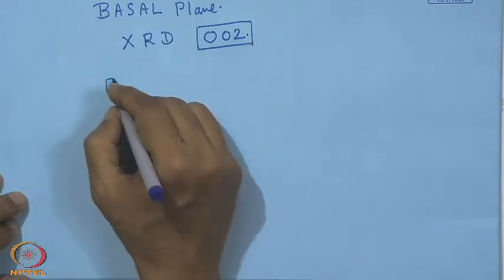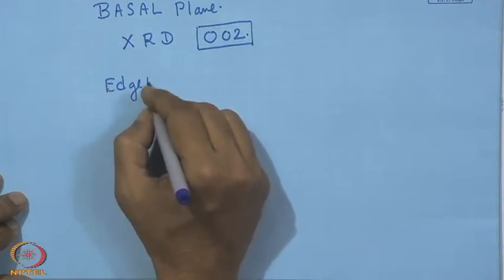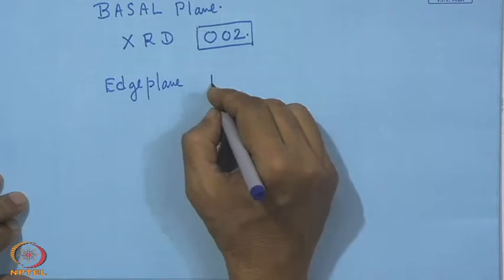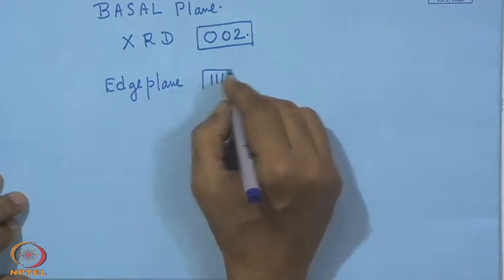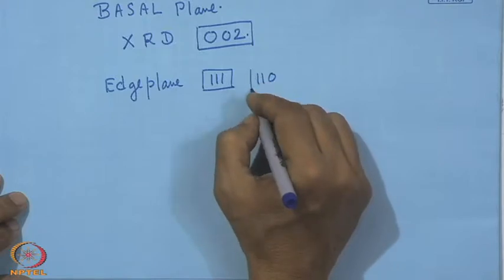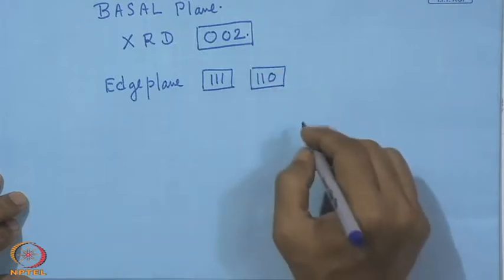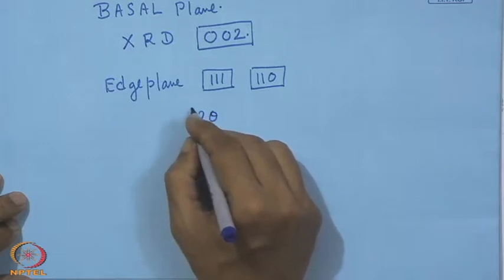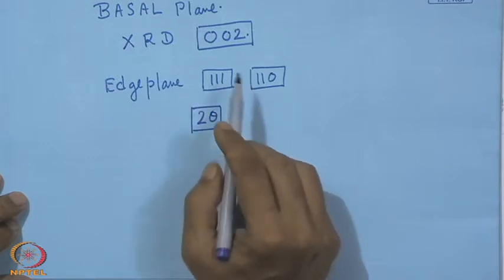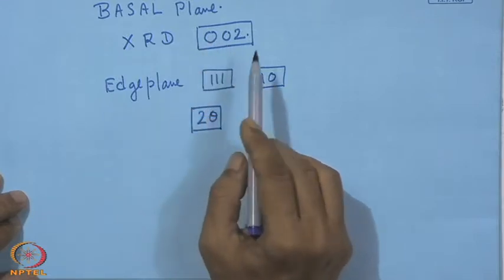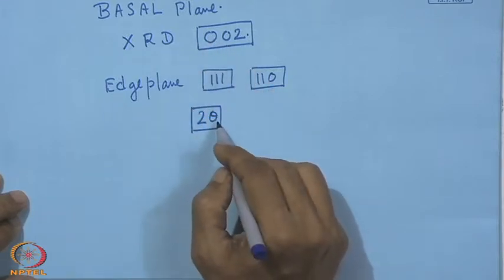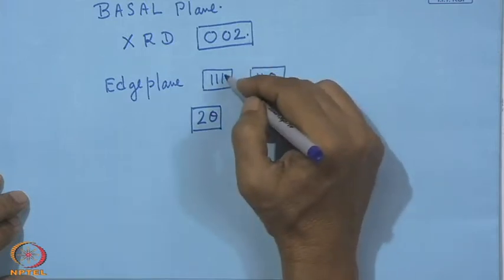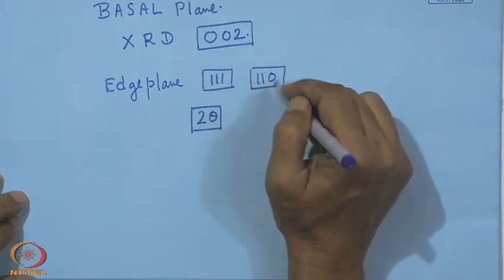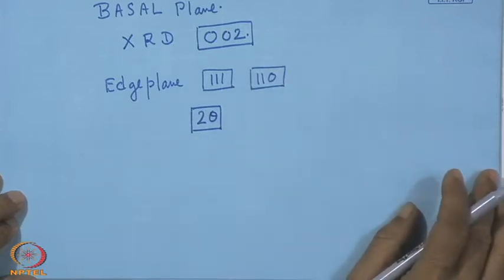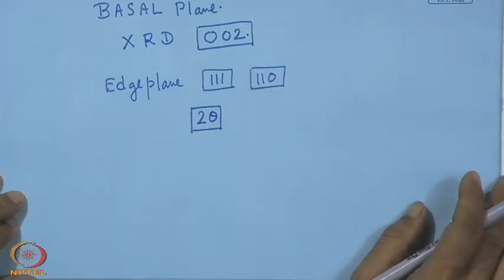It can be edge plane, and in that case the peaks come from this 111 or 110, and for that we have a definite angle 2 theta. And from the standard XRD corresponding to this MoS2, we can find out the value of theta, which corresponds to this 002 or 111 or 110. And from that, concerning the quality of the coating, we can have a fair idea